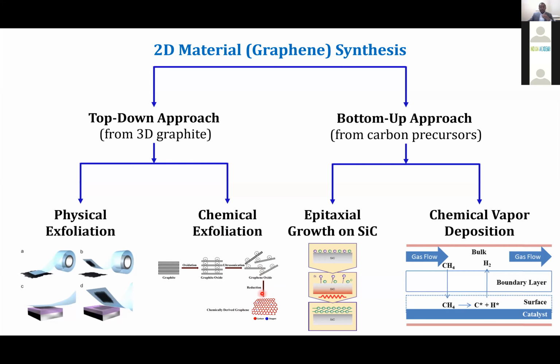So we will be able to form graphene. However, it's called chemically derived graphene because it still has some oxidizing agents attached to the graphene edges or on the surfaces. You will not be able to get rid of all the functional groups that are attached during the oxidation process. Therefore, we still call it graphene oxide or reduced graphene oxide. It's difficult to get pristine graphene out of this process. However, we'll be able to produce graphene in large quantity.